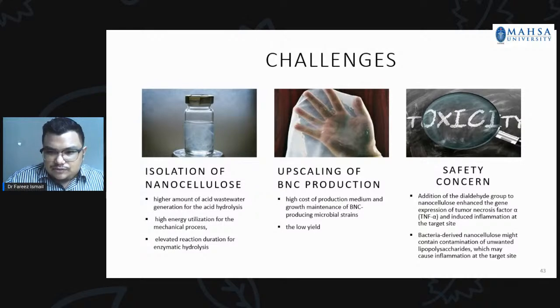Part of that is also related to the toxicity concern. As far as we know, these cellulose are actually non-toxic and non-genotoxic. However, when we do a chemical modification or introduce any chemical into the nanocellulose, it may cause complications, especially when we use it for maybe biomedical application.